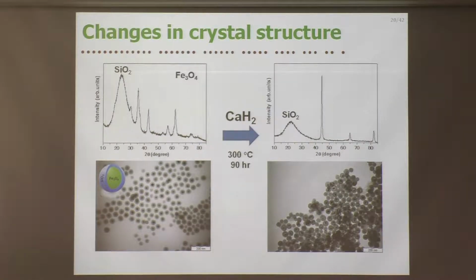Here shows the XRD pattern and the TEM image after reduction. As you can see in the TEM image, the sample still has nice particular shapes, very similar to the starting materials. However, the XRD patterns are now completely different.